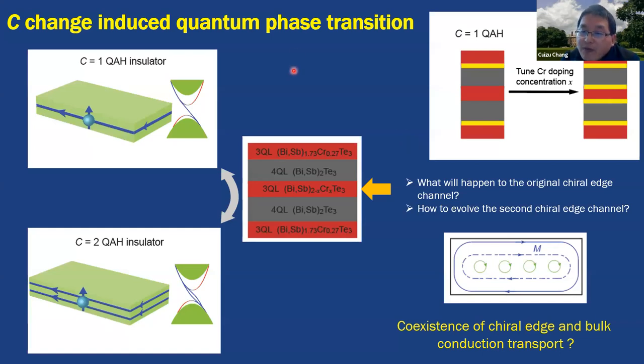And more recently, we further realized this Chern number change induced quantum phase transition. As I just told you, when we tune the chromium doping level in these magnetic topological insulator multilayers, we could tune the Chern number from 1 to 2. Here is the C equals 1 quantum anomalous Hall insulator layer. There is only 1 chiral edge state. And this is the C equals 2 quantum anomalous Hall insulator layers. There are 2 chiral edge states.